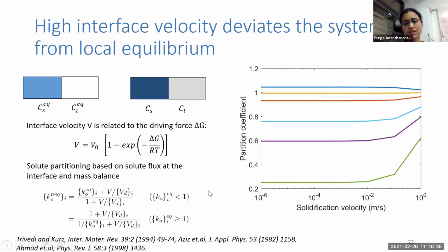So with these two equations, then we can determine the temperature and the composition of solid and liquid, considering this high interface velocity. And just to show what this non-equilibrium partition coefficient looks like, it is related to the equilibrium partition coefficient, the velocity, and this diffuse interface velocity. I'll talk a bit more about this later.